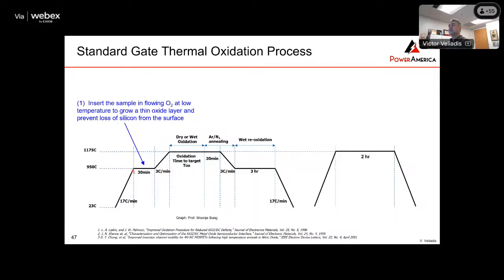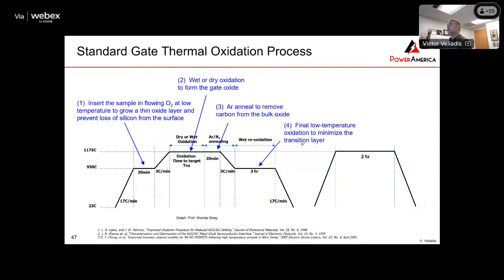So the standard gate thermal oxidation process, you start here. You insert the sample in flowing O2 to grow a thin oxide layer and prevent loss of silicon from the surface. Then you raise the temperature to about 1175 and do a dry oxidation or wet oxidation to form the oxide. The next step is to do an argon anneal to remove carbon from the bulk oxide. And then you do a low temperature oxidation to minimize the transition layer. And finally, and very importantly, you do a post-oxidation anneal in nitric oxide to passivate the interface states. This is the standard process. It's really this nitric oxide that has increased the mobility to the point where we could make useful devices. It was actually a breakthrough, but nevertheless, the mobility is very low.